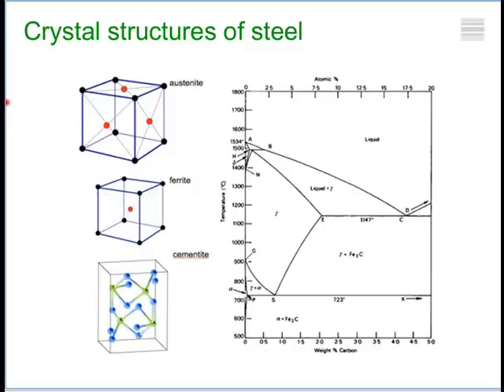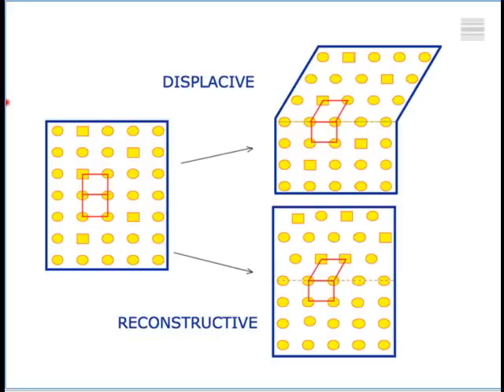Even if they are extremely low carbon steels or heavily alloyed steels, you'll find one or more of these phases in their microstructure. But we have an additional bit of richness in steels, and that is that we can change from one crystal structure to another by many different atomic mechanisms. And just to illustrate the two key mechanisms by which I can change the arrangement of atoms from a pattern like this to another one like this, imagine that this is your austenite, exists at 900 degrees centigrade, and that we have these square atoms and we have these round atoms, let's say iron and manganese atoms.